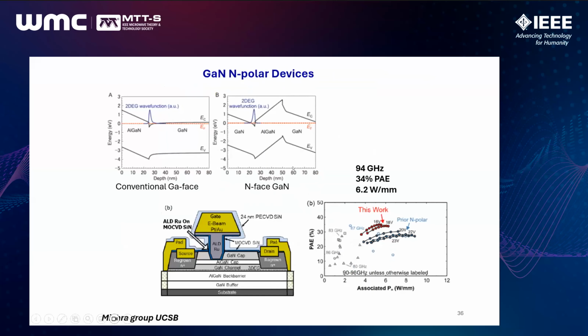Another very important development is the emergence of N-polar gallium nitride, in which case the substrate is flipped upside down, so the 2D electron gas forms on the top surface of the aluminum gallium nitride. And this places that 2D electron gas closer to the surface where it's easy to make very good ohmic contact and to scale device length. This is work that has been done in Umesh Mishra's lab at UC Santa Barbara, in addition to all the other work on the development of nitrides that he has done, and the work for electronics. It's now emerging as something that is getting a lot of attention in areas around the world.